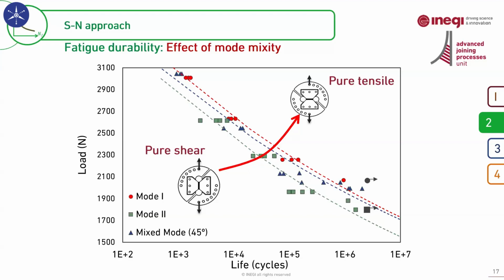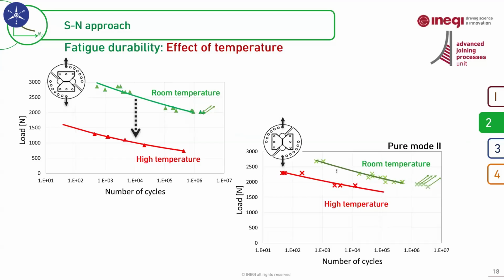But we should note that in reality, stress concentration at the joint edges can strongly influence the result that I show here. Stress concentration can produce high peel stresses at the bonding ends or at critical points of the joint. And that can significantly reduce the fatigue life under pure mode 1, under tensile loading. And that's why a shear dominant design is still recommended. There are other reasons why shear loading is better than tensile, and why we have to design joints to be loaded mainly under shear than tensile.